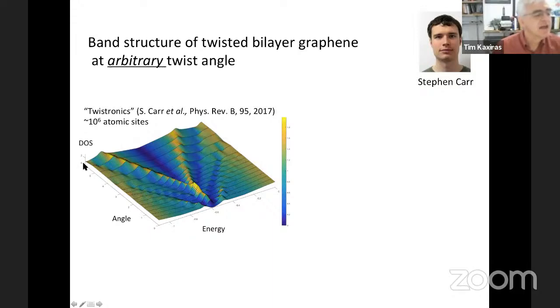So what you see here is the density of states on the vertical axis. It's also color coded. 0 is dark blue and high values is yellow. This is the angle axis going from 0 up to about 5 degrees, 6 degrees. And this is the energy. And again, this is the Fermi level, the position of the Fermi level in the charge neutrality system. So this is the 0 twist. So you have the single layer